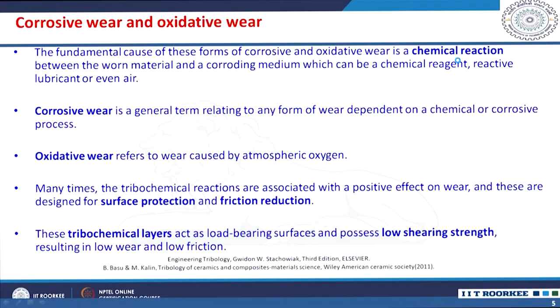The fundamental cause of these forms of corrosive and oxidative wear is a chemical reaction between the worn material and the corroding medium, which can be a chemical reagent, reactive lubricant, or even air. Corrosive wear is generally a term relating to any form of wear depending on a chemical or corrosive process. So, you must have a chemical or corrosive process that leads to corrosive wear, whereas oxidative wear refers to wear caused by atmospheric oxygen. So, if the wear happens in ambient atmospheric conditions, we call it oxidative wear. If it happens in chemical or corrosive conditions, we call it corrosive wear.